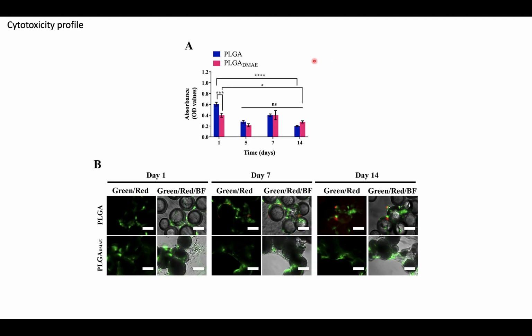We then looked at the cytotoxicity profile of these two macroparticles. We cultured them with the adipose-derived stem cells, and we used a standard assay, the LDH, lactate dehydrogenase assay, to assess the cytotoxicity profile. We noticed that in both cases, modified and unmodified, we maintain a low cytotoxicity profile, and there is no significant difference between the two groups. We also looked at a qualitative assay using a live/dead staining to look at the cytotoxicity profile of these two polymers. Again, we confirm that there is no significant toxicity between the two groups.